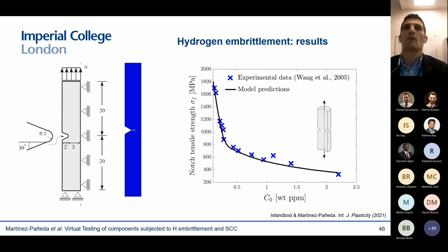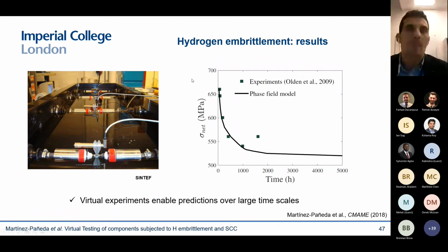But let me show you that we can also deliver quantitative predictions, or quantitative agreement with experiments. These are experiments done in steel bars that have been pre-charged with hydrogen and have a notch. You can see that our model fits the experiment very, very well in terms of notch tensile strength versus hydrogen content. Very good agreement.